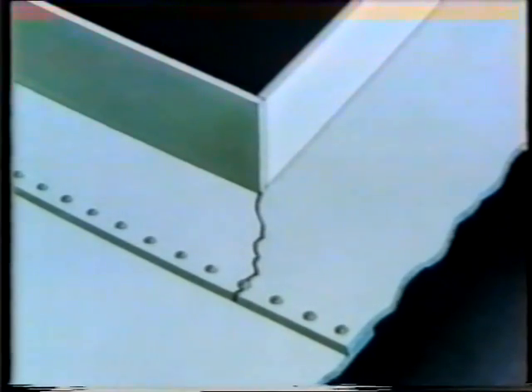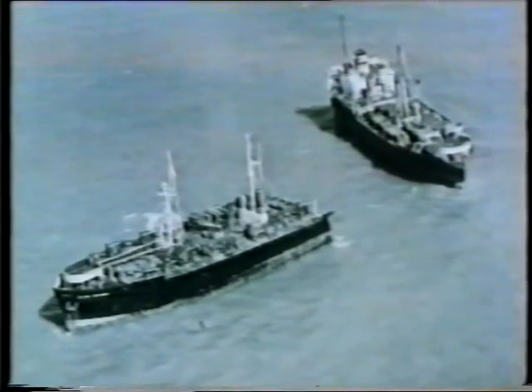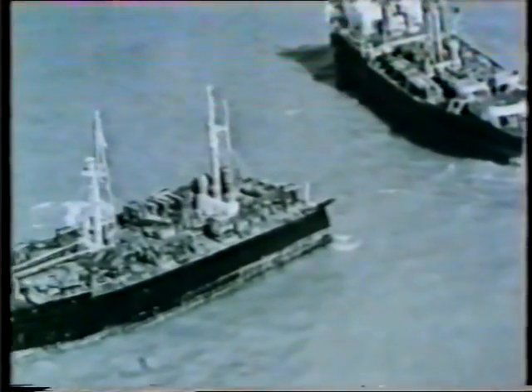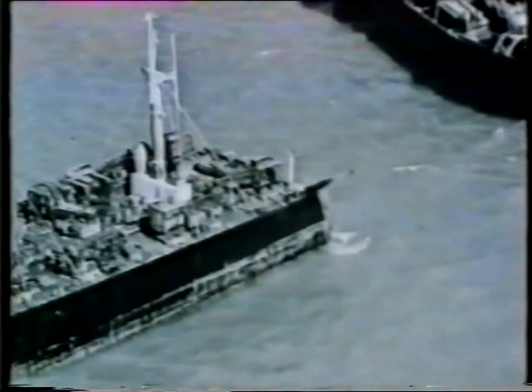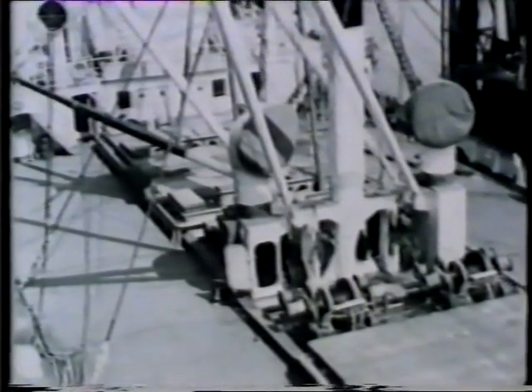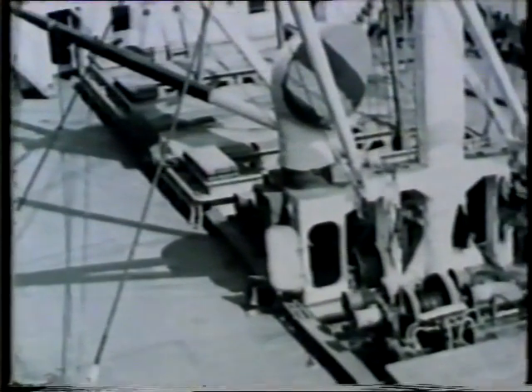The thing that was so different about the Liberty ships was that they were welded. If a crack were to start, it could run right through the hull with nothing to stop it. The ship was effectively a single piece of steel. But even if the square hatch corners were acting as stress raisers and the all-welded hulls had no natural crack arresters, fractures shouldn't have occurred so easily.